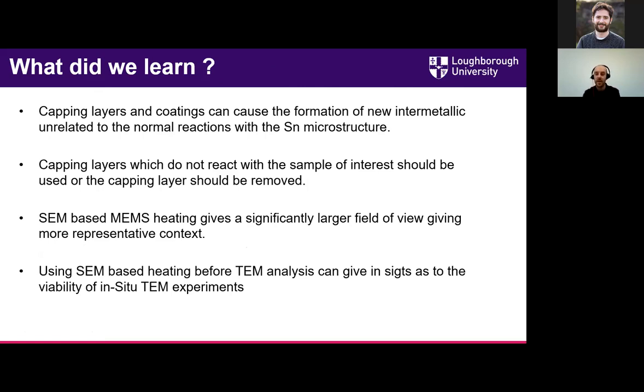If we're looking at tin-based samples, for instance, we need to avoid gold, platinum, and silver coatings, as these can melt and form new precipitates inside the tin. If we were looking at steels, for instance, and we carbon coated the steel before doing some in situ heat treatment, it's quite likely we would form new precipitates because we've got a carbon enrichment on the surface. So either we use capping layers which don't react with the sample, or we should remove the capping layer as much as possible before doing the experiment.